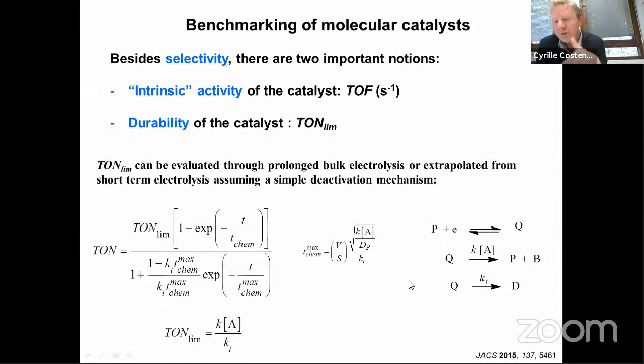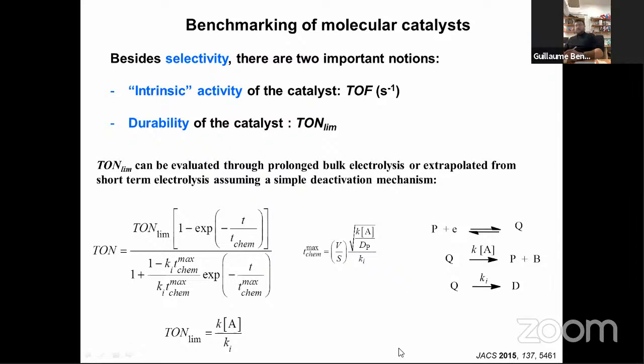Okay, so you also have a diffusion reaction layer if you have a thick film of catalyst. Very similar, but what is diffusing in that case is not the catalyst, it's the electron or the substrate. So this has been described, okay? And this means that if you want to get the true intrinsic activity of your catalyst, you have to know how many molecules you're able to activate, because you have to report the amount of product you make to the amount of molecules that you have actually activated. Okay. Yeah, thank you very much.